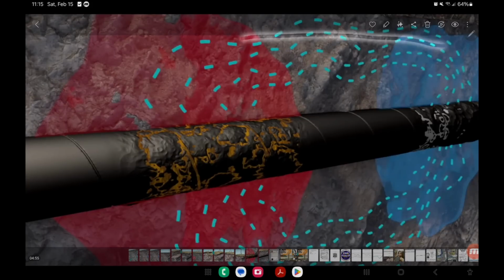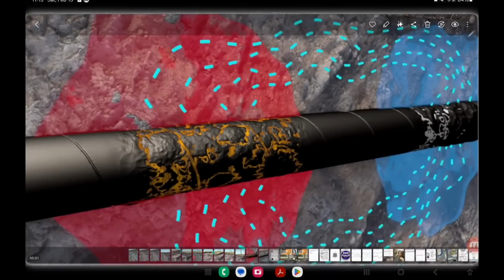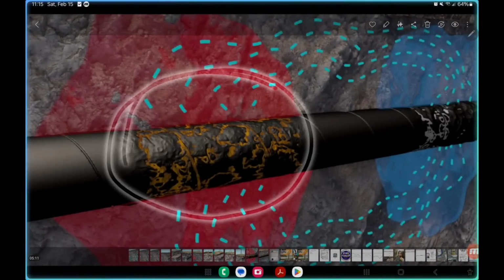Gentlemen, this is the zone where the area that corrodes is presented. Normally we will see it, we enter nuance. For example, let's suppose that here they replaced the pipe because it was damaged in the past and they installed a new pipe. But it happens that the new pipe has more energy. It has greater energetic properties compared to the old one, and the same vicious cycle will always occur.